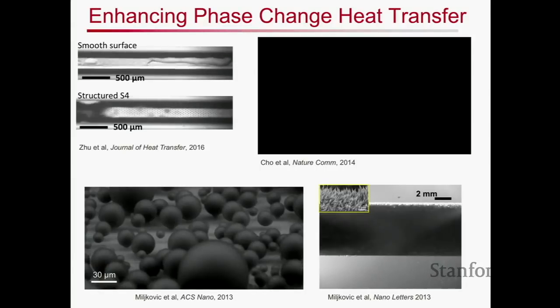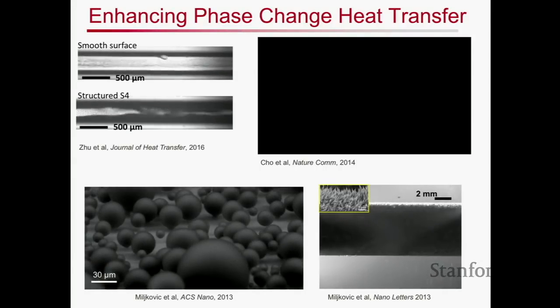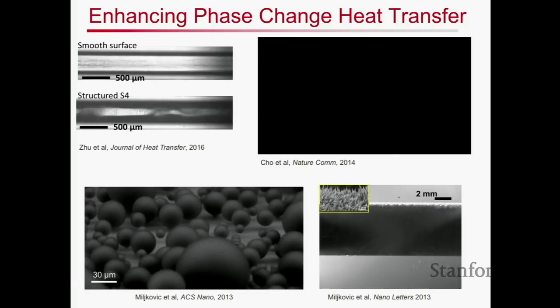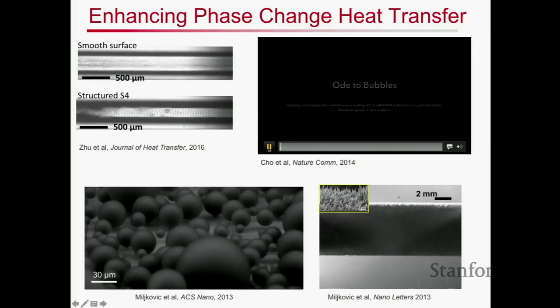which becomes detrimental in a lot of these liquid to vapor phase change processes. What she's shown is that if you incorporate various types of structures onto the backside of this system, then you can improve stability significantly in this case. And that could allow us to better manipulate that liquid to vapor phase transition. We've also shown, through time, in the video on the right, that we can control much better the liquid to vapor phase change.